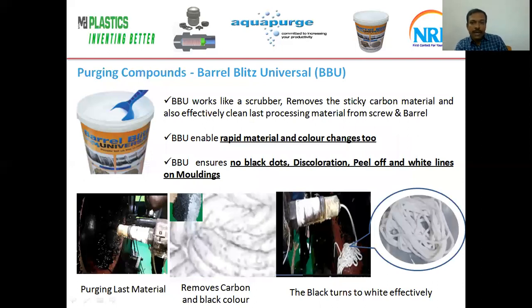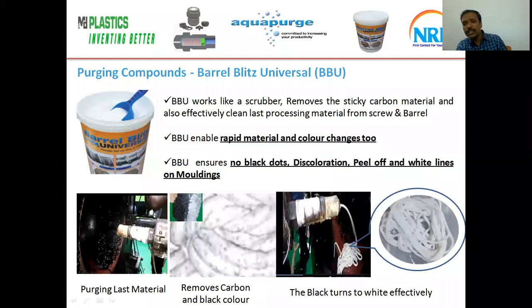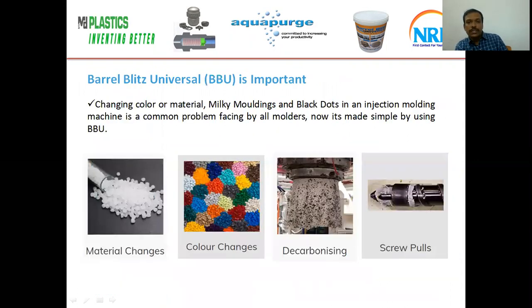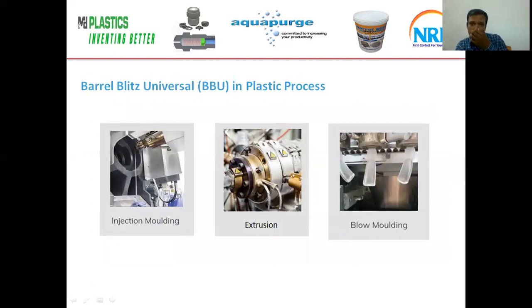So I'm going to introduce Barrel Blitz Universal. It works like a scrubber, removes the sticky carbon material and also effectively cleans the last processed material from the screw and barrel. BBU enables rapid material and color changes too. BBU ensures no more black dots, discoloration, peel off and white lines as molding defects. See here I have shown some photographs of purging: the last material, carbon black material removed, then it turns white effectively within 40 minutes. The purging material can be used when changing material, changing color, decarbonizing, removing carbon on moldings and removing the screw from the barrel. The purging compound, like BBU, can be used in injection molding, extrusion and blow molding also.